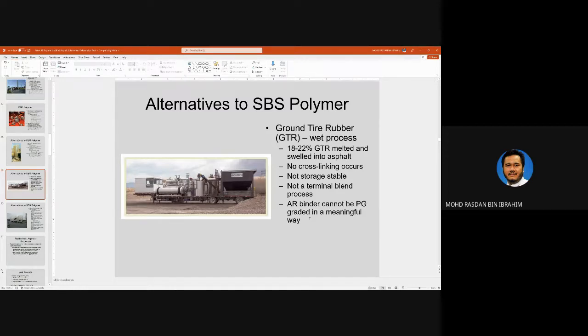So recent research have noted that they have started to use finer rubber particles. I have studied in my PhD crumb rubber modified asphalt actually. So I have found that we need to at least use 80 mesh rubber, meaning that the size is 0.1 mm, 0.2 mm or less. That type of mix produces a better mix compared to bitumen that has been modified by coarser rubber particle size.